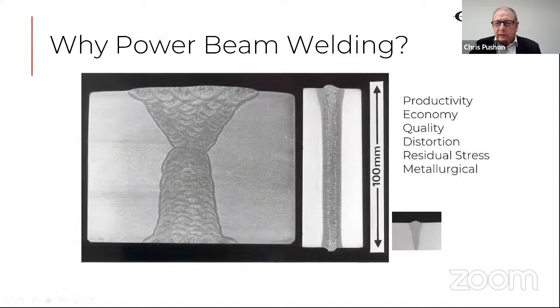So just to illustrate the drivers for power beam welding, what you see on the left-hand side is a multi-pass submerged arc weld. This is a low heat input submerged arc welding process. And what you see is we have to make a double-sided V preparation, and then we replace the material that's gone with a flux-shielded wire deposition. And if you very quickly count these passes, you see 70-odd weld passes in this joint. You also have to preheat the material before you weld. And if you make a defect buried in the middle here, you have to excavate quite a large amount to repair it.